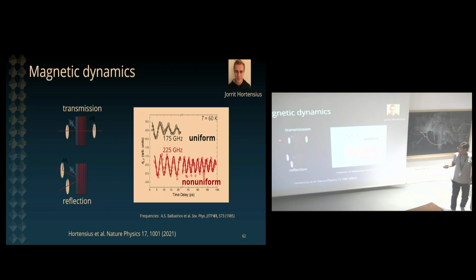This is an experiment that was done by Jorrit. Here, at the same time, we are probing, in this dysprosium orthoferrite that has been excited at this particular resonance, both transmission and reflection. You see that in the transmission mode, Jorrit is measuring through Faraday rotation oscillations of the uniform spin precession mode at 175 gigahertz. However, when he turns on the detection in the reflection scheme, he now sees an oscillation occurring at 225 gigahertz.